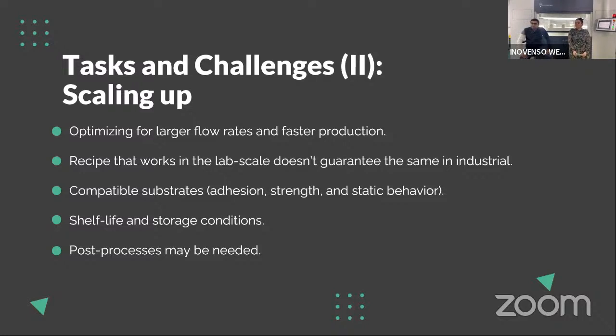And finally, the substrate needs to have an anti-static property. So its static behavior matters. In the past, some substrates that you're using, like spunbond media, for example polypropylene, which is really well known, tend to accumulate charge. If it accumulates charge, it can basically repel the fiber jets. So that's something that you want to avoid. For the case of polypropylene, it's not biodegradable, but you could treat it to make it have anti-static properties. But yes, your substrate needs to be anti-static. Otherwise, if you were to electrospin it, you'll notice some regions where the nanofiber layer membrane wasn't homogeneously distributed. So that's something you basically need to think about before continuing onto the industrial scale.